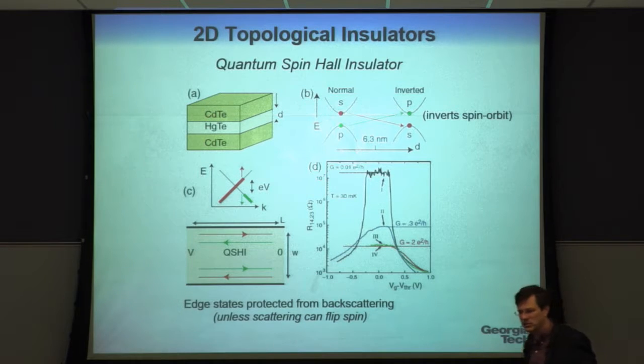The concept for this actually came from Charlie Kane and Gene Mele at University of Pennsylvania. They were looking at graphene, but they introduced, in fact, they actually made a mistake in the original paper. They had spin-orbit coupling that was too large. But they realized some key things about that system, some key topological aspects of that system. And so the graphene played a really important role in developing this concept of two-dimensional topological insulators, also called quantum spin Hall insulators. These were first realized in a II-VI system, cadmium telluride, mercury telluride, cadmium telluride.